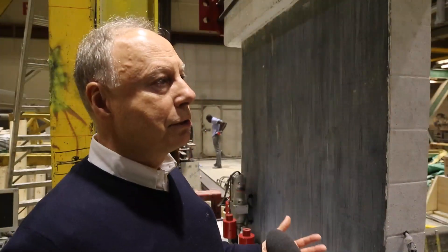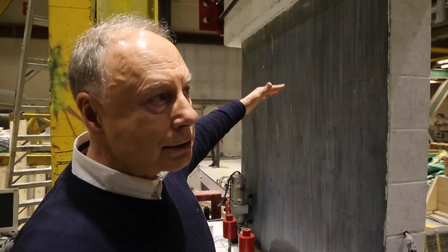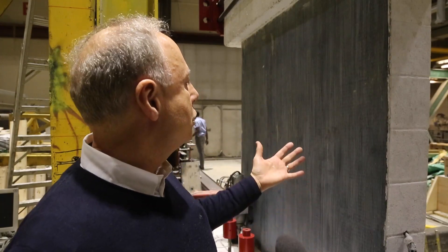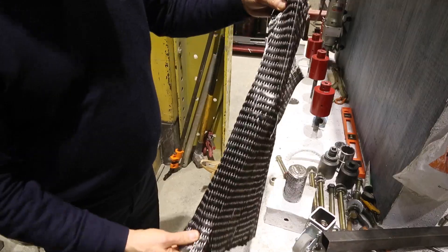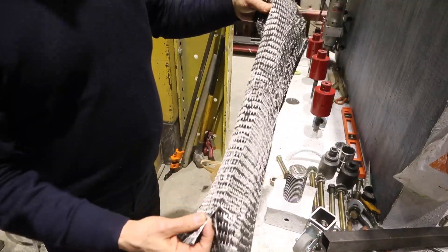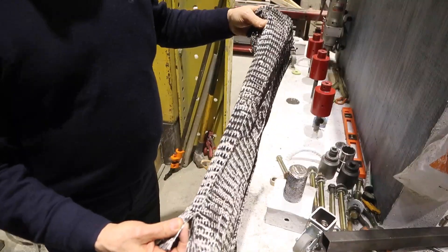Another dominant form of failure in masonry walls is shear failure. Shear results in diagonal cracks along the surface of the wall. To prevent that, we use this high-strength material — fibre reinforced polymer sheets, known as FRP sheets — epoxy glued on the wall to control shear.